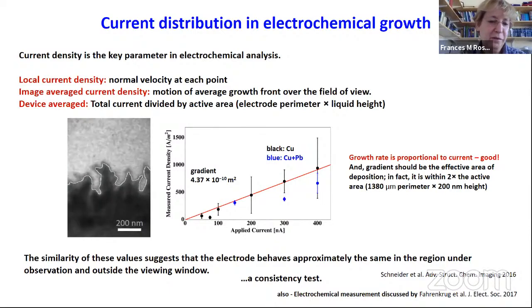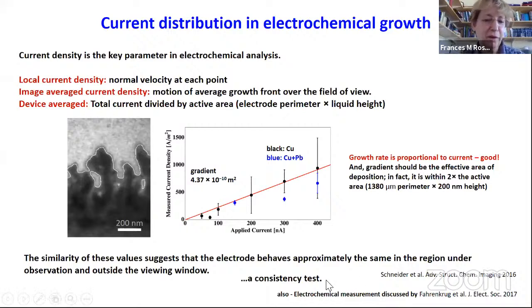Here's another one. Here's the movie I showed of dendrite growth coming off the edge of an electrode. And we can ask ourselves, what is the local current density in the experiment? So we can count up how much copper is deposited, and we can convert that into a current density along the edge of the electrode, and we can compare that with the total current that flows in the experiment. But also we can compare the growth rates with the total current in different experiments. So if you do two experiments with two different total currents, does the material actually grow twice as fast in one case compared to the other? And the answer is yes, it does. The growth rate is proportional to the current. And so we have, again, a consistency test that helps us understand what's going on.